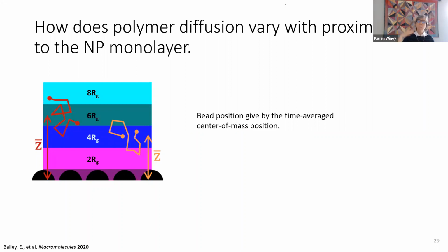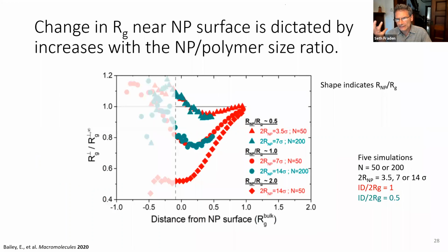Because we have this very intuition on this, why you have a compression, I almost would expect the opposite, that because of entropy, it would be less compressed. I don't know, avoid the surface or something. Yeah, so interesting, I glossed over this, but when the nanoparticle is smaller than its radius of gyration, you do get a little bit of an increase here before it decreases.